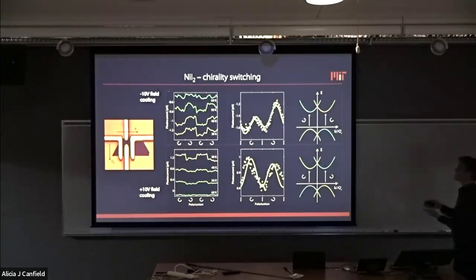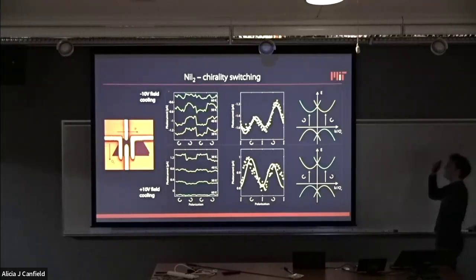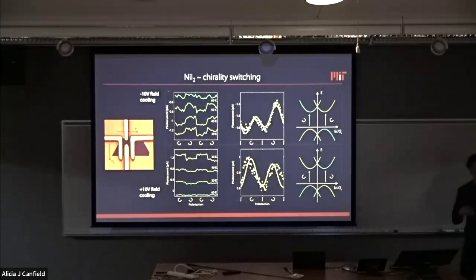So we see that the chirality basically switches. When we do a negative electric field poling, we have one particular chirality, so we have one type of trace. When we pole with a positive electric field, that chirality is switched. So here it's positive, and here it's switched to negative. And so we can keep track of that. And this confirms that the chirality is really rigidly coupled to the polarization, which now introduces this interesting possibility of controlling the chirality using the electric field.